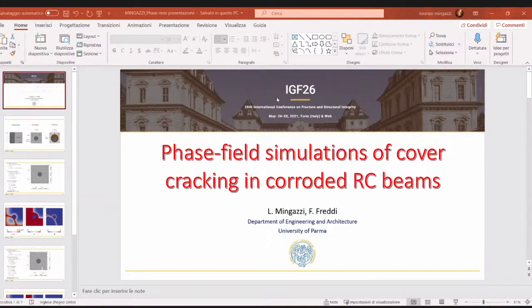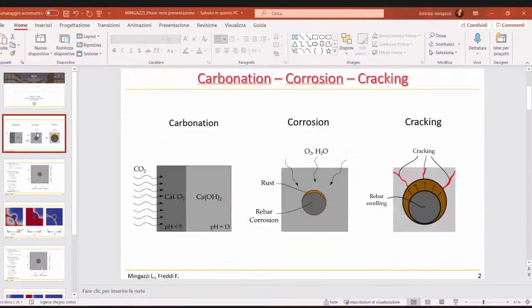The main idea of our research is to develop a predictive model which is capable to provide accurate estimates of this corrosion cracking phenomenon for reinforced concrete structures. The simulation is structured by studying the three main phenomena which form the carbonation corrosion cracking. First we model the carbonation process via standard diffusion reaction equation, where the carbon dioxide enters through the pores of the concrete covers, and due to the chemical reactions, the carbonation of the concrete takes place.